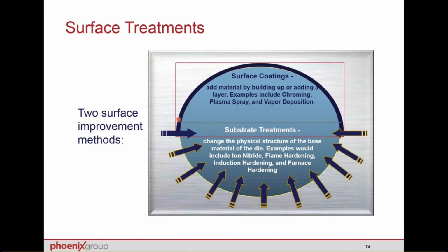Some of the vapor deposited coatings are only 2/10,000ths of an inch thick, so there's no opportunity to grind on them. But what they do bring to the die is a very, very hard wear-resistant surface that also does a great job of reflecting or transferring the polish from the underside, whatever the die is polished to. These will mirror that polished finish. So I can polish the die very, very substantially, give it a nice mirror finish, put on one of these coatings, and preserve that shape for a long period of time.